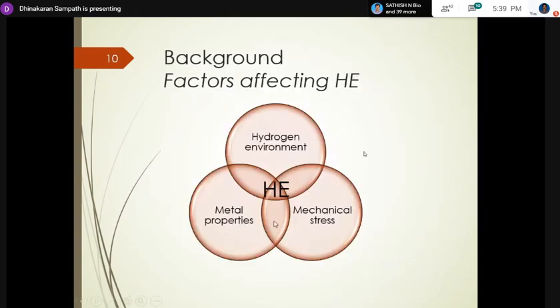So for the factors affecting it, we need all three components: hydrogen environment, material properties. I mean here, high strength alloys are very deleterious. And also if we have phases in the grain boundary, which is also detrimental, it will promote grain boundary cracking, intragranular cracking. And mechanical stress, again, is very important, either sustained or fatigue loading. And the hydrogen environment could be electrochemical based or gaseous based. So all of these environmental parameters play a role in the susceptibility of a material.